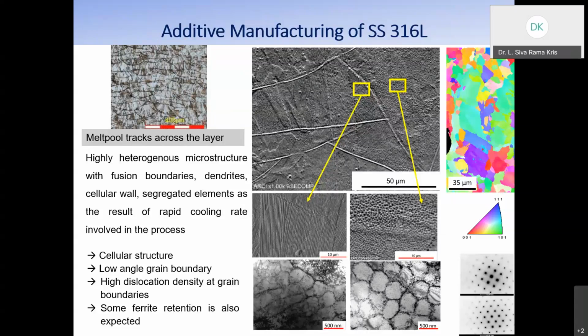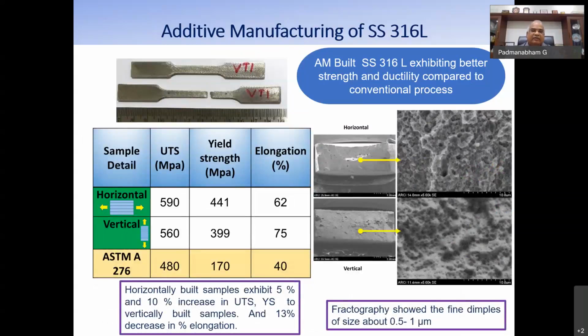So we can see effects of rapid solidification in terms of a cellular microstructure, very low angle grain boundaries. You can also see high dislocation densities at grain boundaries with some ferrite retention, which gives you ductility also. So these are the typical features we encounter in an AM built stainless steel, even if it's a single phase material. And what it shows up as, you can see the yield strength going from a conventional value of 170 megapascals to 441 or 399 in the two directions of the samples taken from an AM built structure. And typically, this is coming from the microstructure, which I have explained.